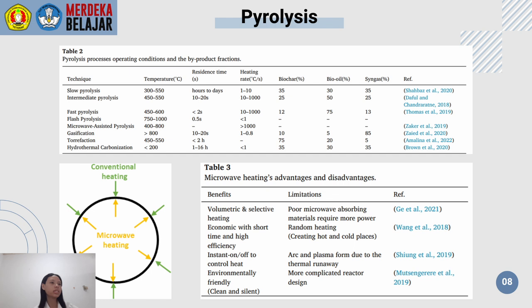If the desired product is bio-oil, the optimal pyrolysis temperature range is 425 to 600 degrees Celsius, with maximum heat less than 650 degrees Celsius. However, if gas generation is the main objective, the peak temperature can reach 1000 degrees Celsius. Finely ground biomass feedstock, often less than 1 millimeter, is required to produce very high heat transfer rates and consequently very high heating rates, reducing mass and heat transfer constraints.